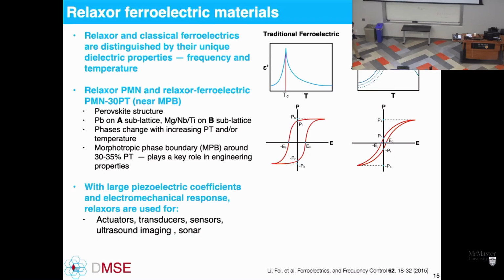What we've talked about so far are conventional ferroelectrics and conventional antiferroelectrics, where essentially at a particular Curie temperature in a ferroelectric, you'll get a very sharp onset of a very sharp change in the dielectric function, in comparison to a relaxor, where this is a much more spread out transition in temperature, and as a result, basically, that behavior is spread out across a wider temperature range.